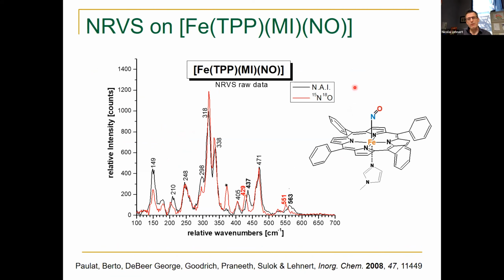So here is probably the first data set that we ever measured at the APS, right? This is data on this model complex here. This is just on powder. The spectrum in black with natural abundance isotopes NO, and then the spectrum in red with 15N18O labeled NO. And you can see there are 2 modes that are isotope sensitive that show shifts when you label the NO. Right? And again, this is the data here in raw intensity or in counts on the detector.